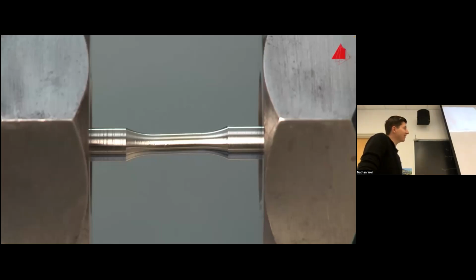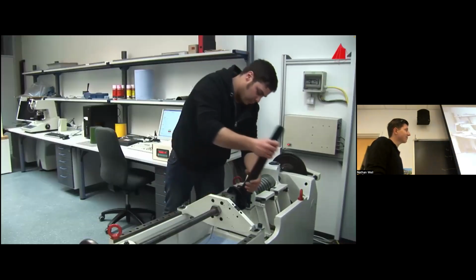In reality, however, several cracks have already developed on the surface, the so-called fatigue cracks. With each load cycle, they grow a bit further into the specimen. The biggest crack gains the upper hand, grows the fastest, and finally leads to fracture after 381,000 load cycles. The first test is finished.